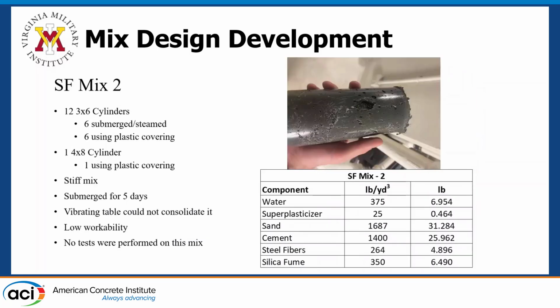Silica fume mix 2. This is what happens when you don't use enough water. As you can tell, there are large voids. It was a very stiff mix to work with. Cut my hand a few times, to say the least. Not very fluid, very hard to mold. It did not consolidate using a vibrating table, which I found incredibly interesting. No tests were once again performed on this mix. Granted, the large voids would completely offset the strength we were getting.